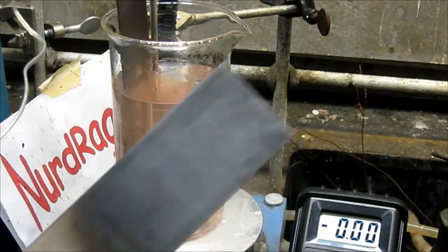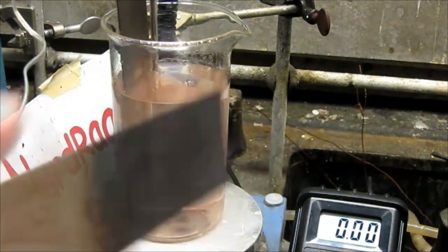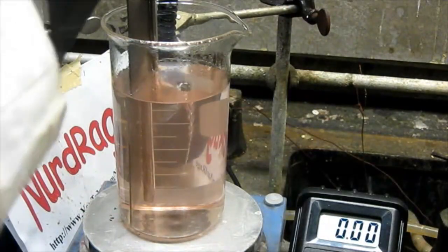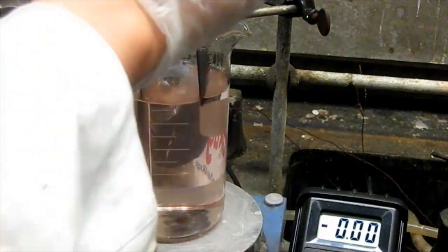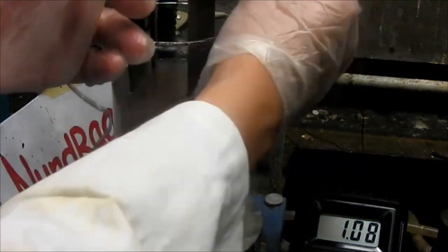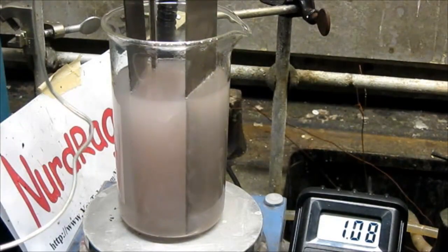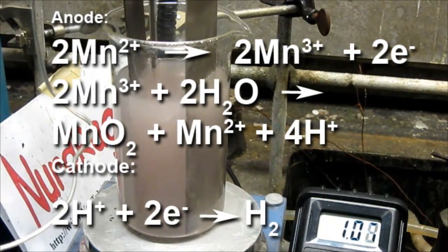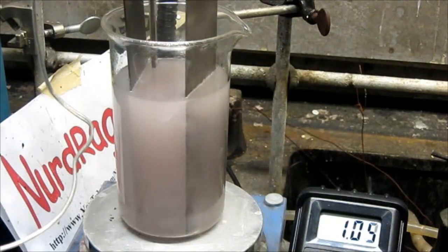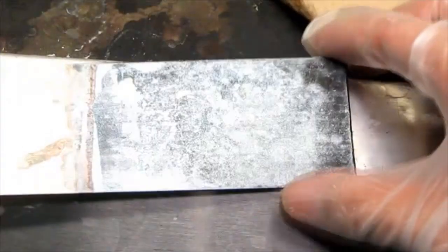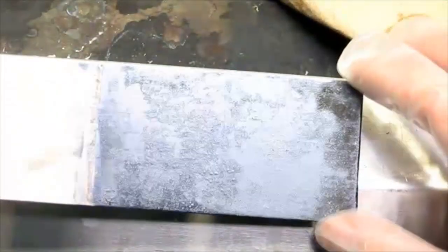Now, making the manganese dioxide electrode as the anode, run through a current of up to 10 milliamps per square centimeter. In this case, I've got a two-sided electrode of 50 square centimeters each, so that's 1 amp in total. As it runs, manganese dioxide is deposited onto the electrode. The manganese 2 ions are oxidized to manganese 3, which in turn disproportionates into manganese dioxide. I ran this for about 5 minutes. And now we have a deposit of hard manganese dioxide.